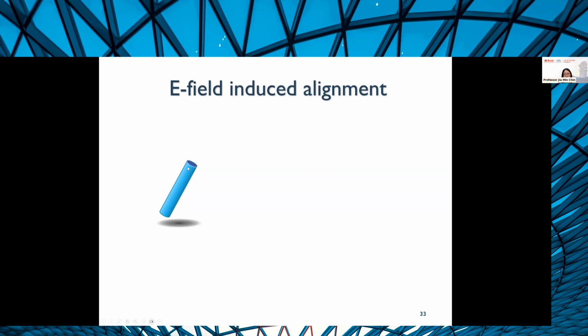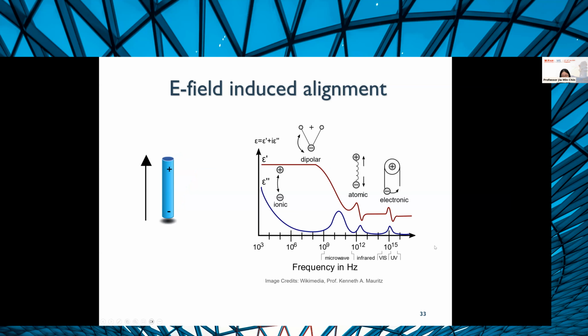So if you consider a particle or a rod or any material really, stick it inside an electric field. If you have appropriate frequencies and appropriate polarizability of your particle, you will induce a dipole in your material. This induced dipole gives you a torque, and these particles then align along the electric field. This is very frequency dependent. If you use low frequencies of your electric field, you induce a dipole via ionic movement. And if you use higher frequencies, you can induce dipoles via dipolar polarization and so on. Typically we stay in this range here because that's the limitation of the instruments we have.